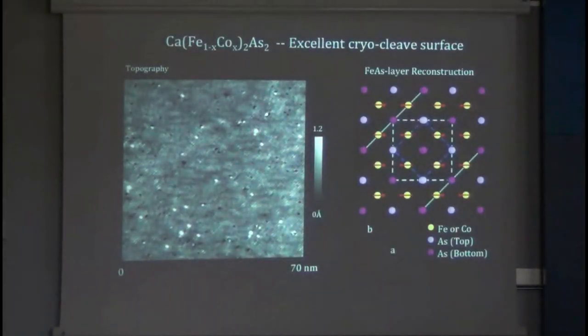This compound has a beautiful surface. Up until this point, which was sometime in 09, there had been many attempts to use spectroscopic STM to visualize the electronic structure of iron superconductors, but they really were prevented from having major scientific successes because the cleave surface, the surface which is revealed by breaking the crystal of most of those compounds, is disordered and charged and is a big mess. Paul Canfield, the genius that he is, proposed that because calcium is soft, you'll be able to break these crystals and get a nice surface, and he was exactly right.